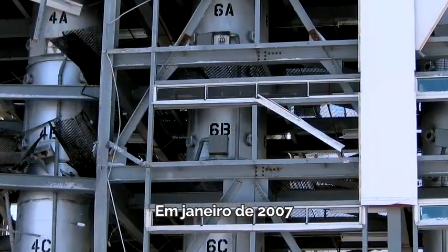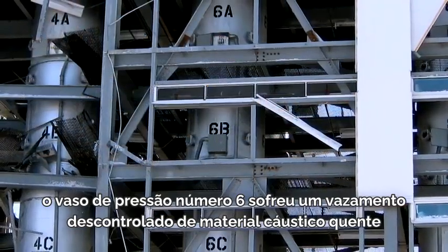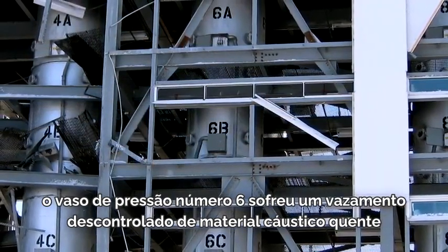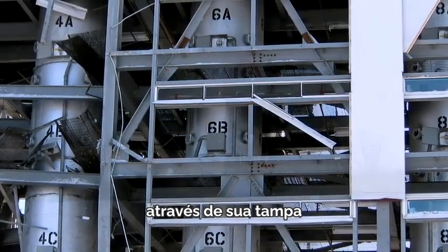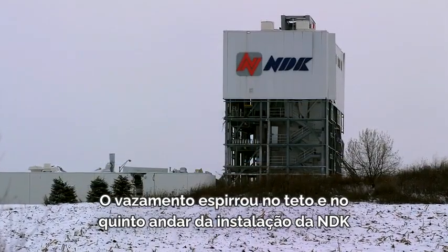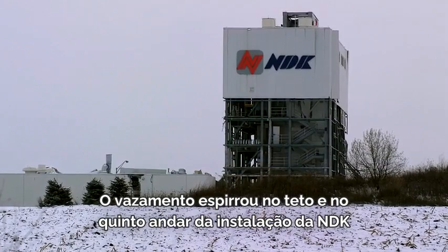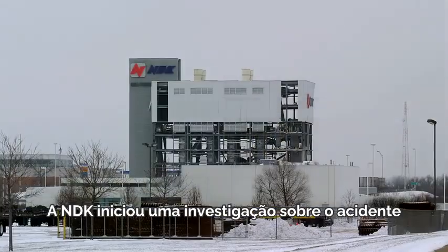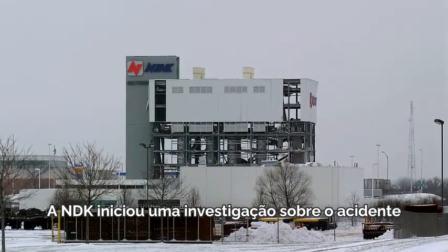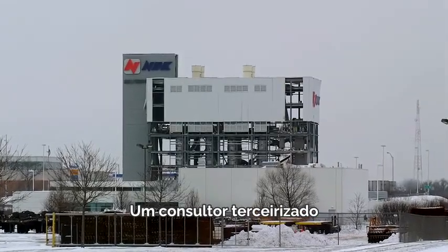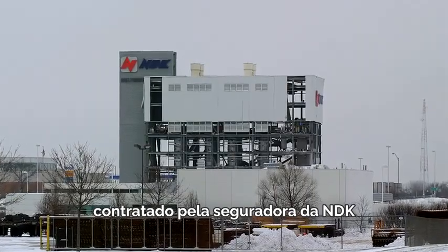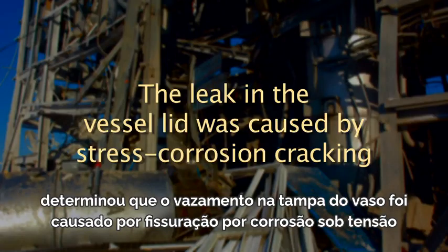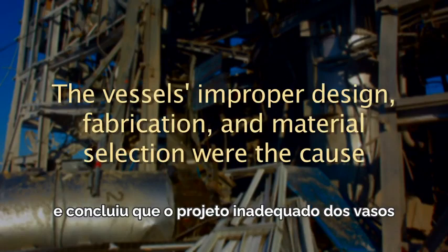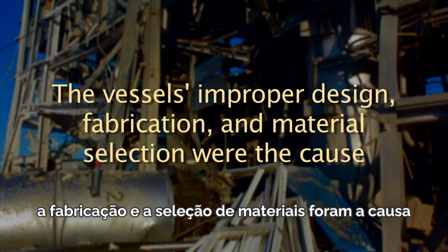In January 2007, pressure vessel number 6 experienced an uncontrolled leak of hot caustic material through its lid. The leak sprayed onto the ceiling and 5th floor of the NDK facility, but caused no injuries. NDK initiated an investigation into the accident. A third-party consultant, hired by NDK's insurance company, determined that the leak in the vessel lid was caused by stress corrosion cracking, and concluded that the vessel's improper design, fabrication, and material selection were the cause.